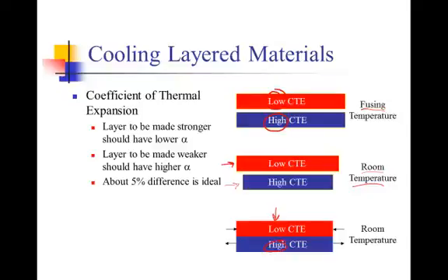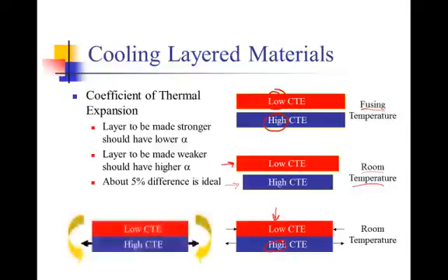If we go beyond this, then we crack the surface material and develop what looks like the crackle glaze effect that you see in many traditional Asian vases made of ceramic. We don't want that on the surface of our dental restorations. And then we have an animation down here that I will save and use for our discussions later in class.